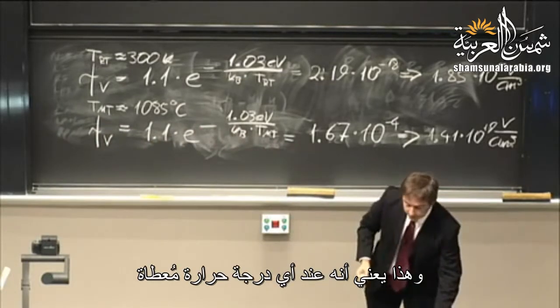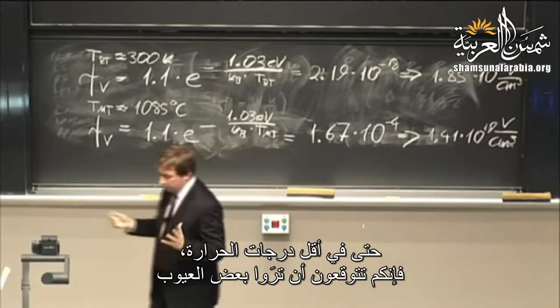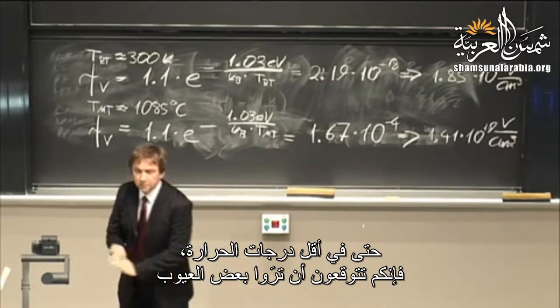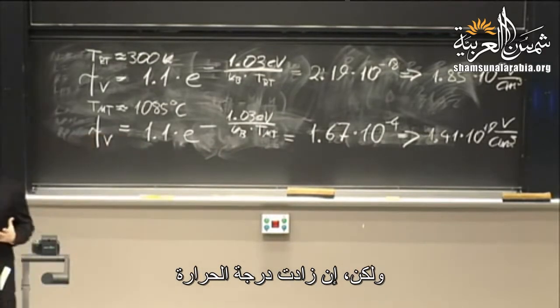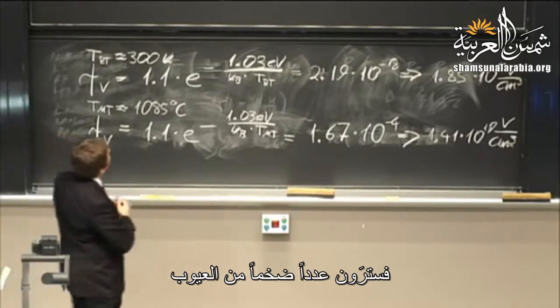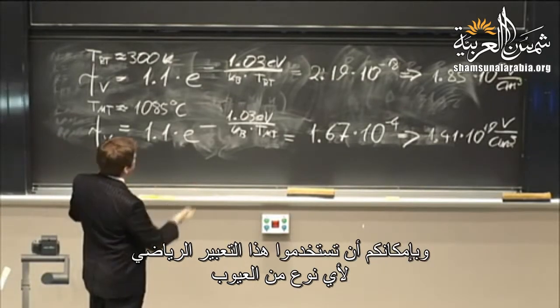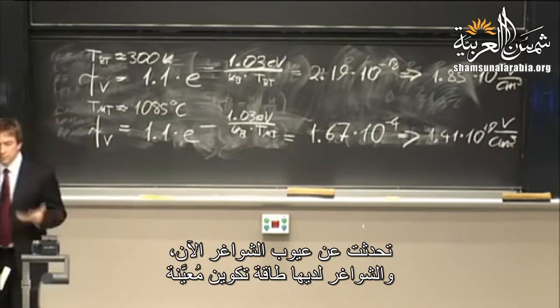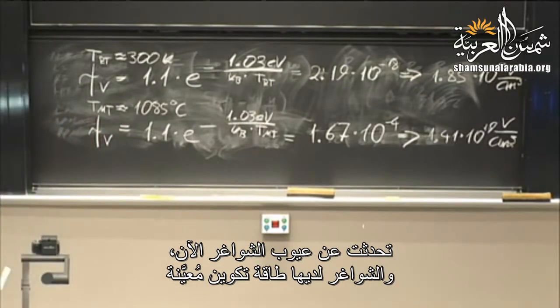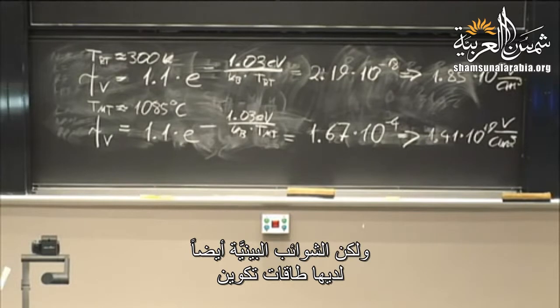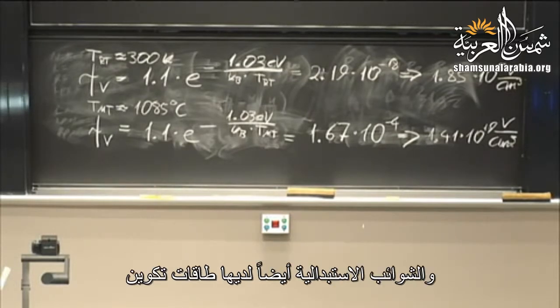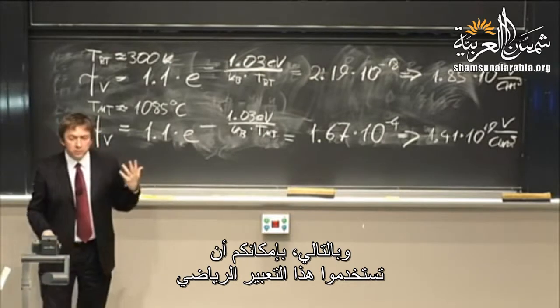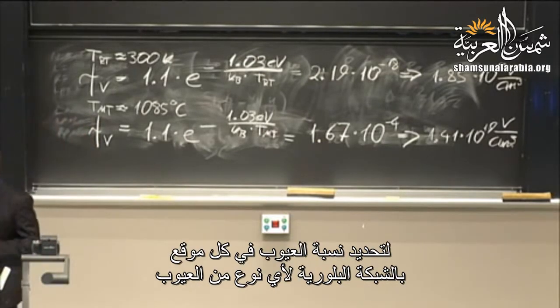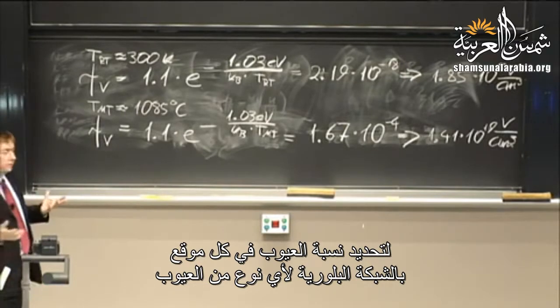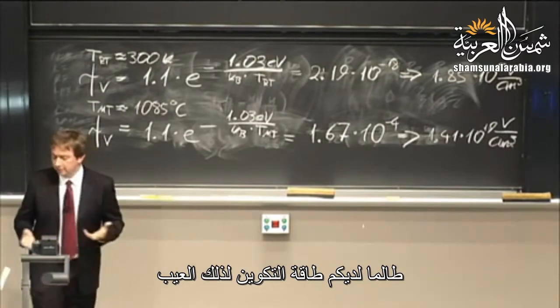So that means that at any given temperature, even the lowest temperatures, you expect to see some defects, but if you increase the temperature, you see a hugely larger number of defects. And you can use this sort of expression for any kind of defect. I talked about vacancies right now, and vacancies have a specific formation energy, but interstitials also have formation energies, substitutionals have formation energies, so you can use this expression to determine the fraction of defects per lattice site for any kind of defect, so long as you have the formation energy of that defect.